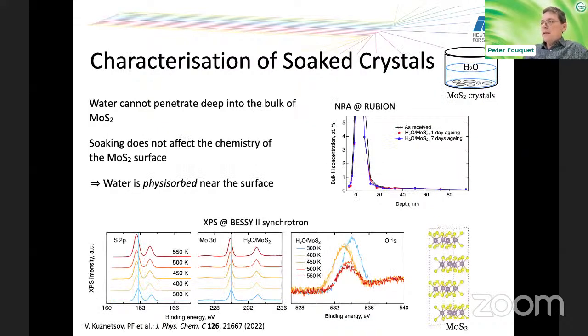Now, then we exposed them to the different techniques that are at our hands. So for the soaked crystals, just soaked in demineralized water, when we looked at them with nuclear reaction analysis, where you expose the samples to an ion beam, you can look at the depth profile of the hydrogen. And there you see basically no hydrogen in the sample beyond the absolute surface layer. There's no signal in the deeper depths.